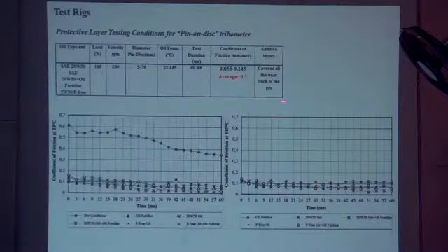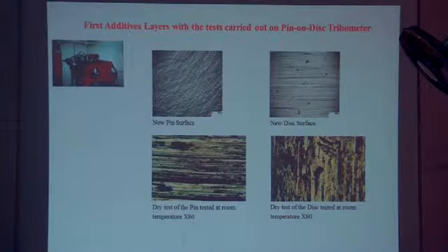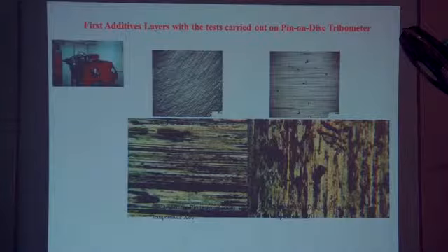That's very interesting. I would like to take your attention here. The boundary lubrication friction coefficient was 0.1 as an average. So we did friction tests with different kinds of oil. This is the pin surface, this is the disk surface, and there is no oil here because this was a dry test. First of all, I wanted to see what happens in the dry test, I was curious about it. And it's all worn out, scuffed. You see, the surface is not very interesting.